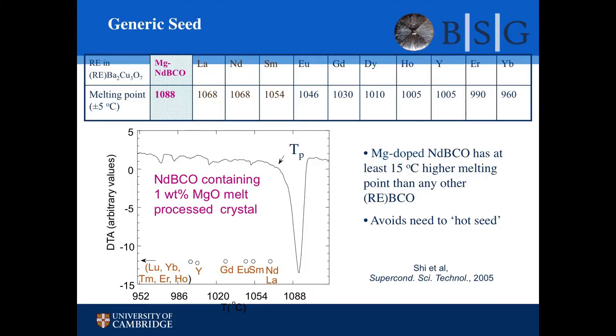What seed do you use? Well, for a long time we used magnesia, and lattice mismatch was very big, gave us fairly poor properties. But actually, Huar, as part of a PhD, developed a new generic seed, magnesium-doped neodymium barium copper oxide, and you get this big leap in decomposition temperature, 20 degrees. And we can use this seed now to grow any one of these materials.